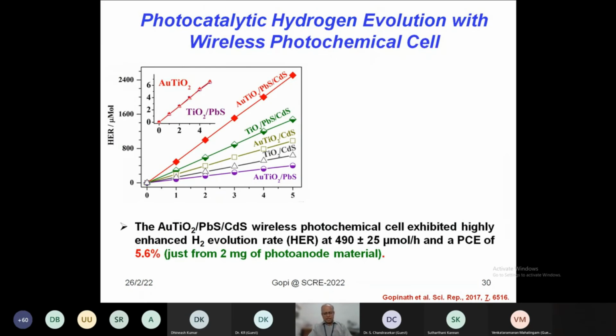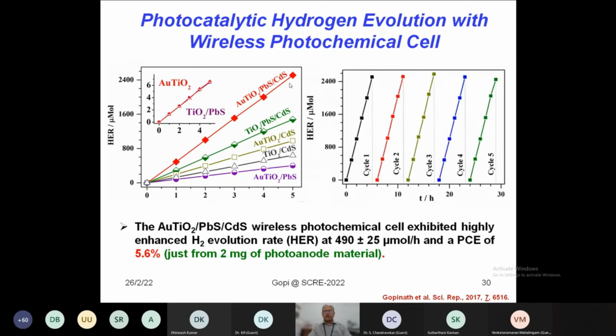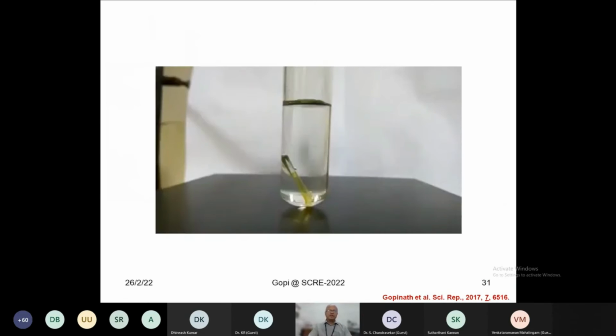So that's the first thing. Like that, we made several photoanodes and measured the activity, and we could see maximum activity with the gold, titania, lead sulfide and cadmium sulfide, which we also evaluated for several cycles, and the activity seems to be stable. With a 1 square centimeter film, which contains about 2 milligrams of the photoanode material, it gives about 500 micromoles of hydrogen per hour in the presence of sunlight, or one sun condition. This is with 2 milligrams of material I'm talking about, 500 micromoles. So you can imagine.